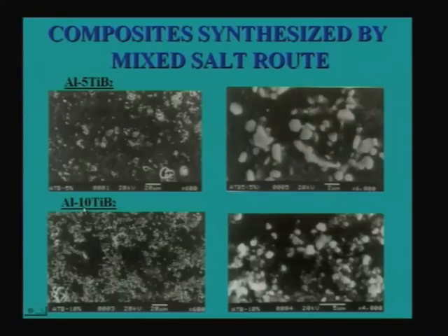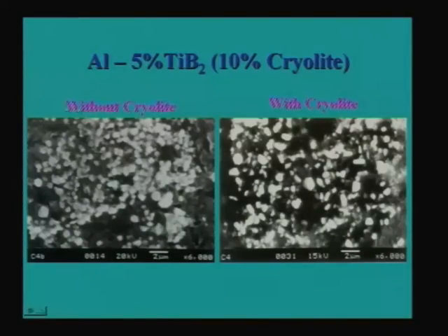How do we convert weight percent to volume percent? Whenever you are talking of a composite, we usually refer only to volume fraction. Whenever I say aluminum 20% silicon carbide composite, we are not talking about weight percent of silicon carbide, we are talking of volume percent of silicon carbide. So how do we convert it? By considering the densities of the two phases. So once we know the density of the two phases, one can calculate the volume fraction.